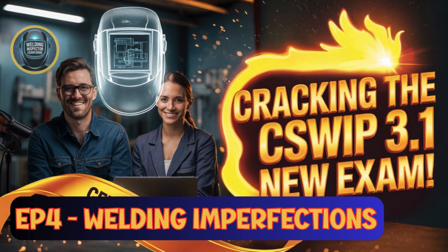Yeah. But if it's deeper, like internal slag or lack of fusion? If the defect is too deep for simple dressing, or if it's internal, it must be completely removed. This usually involves excavation, meaning you physically cut or grind out all the defective material and a little bit around it to be sure. Okay. And then new weld metal must be added to fill that excavation and restore the joint to ensure the minimum required design thickness and strength are achieved. And I assume that repair welding isn't just done any old way.